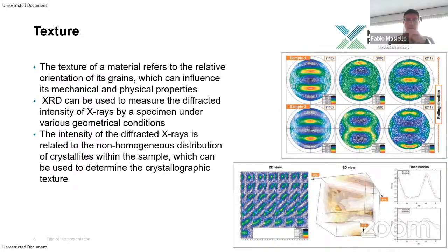For example, on the right side, you see what we call a pole figure. Practically, it's the intensity of a certain peak, for example 110, 200, as a function of, let's say, sample orientation. And by making use of this pole figure, it's possible to reconstruct things like the ODF and get an idea of what the crystallographic texture in the sample is.